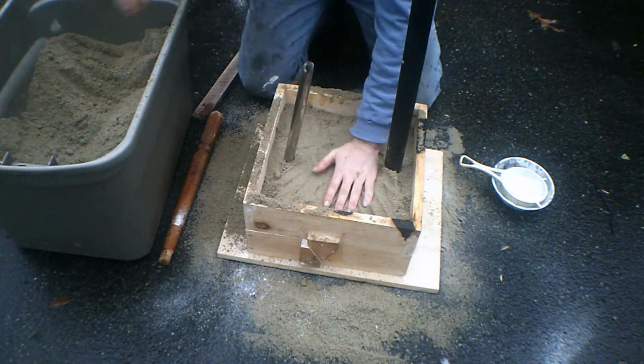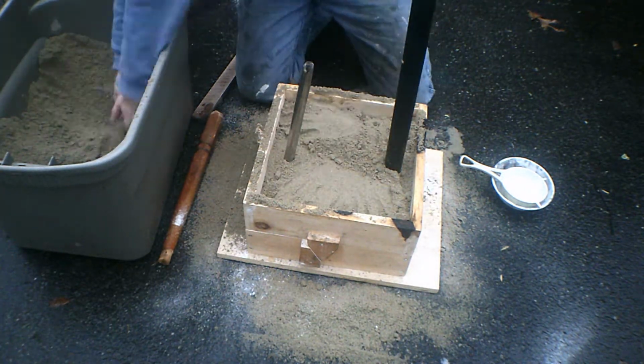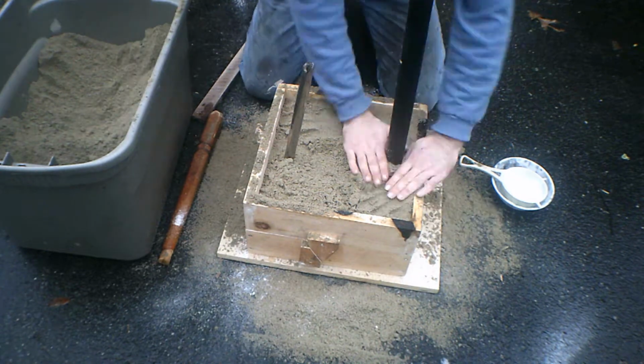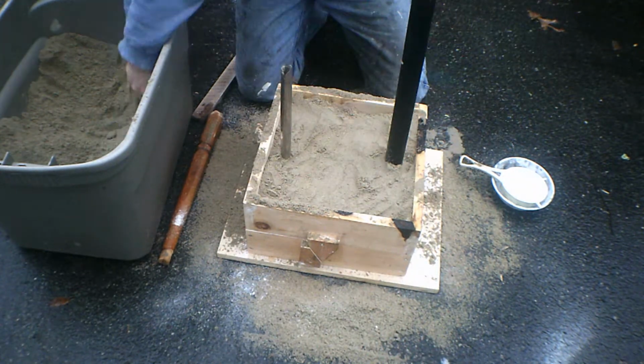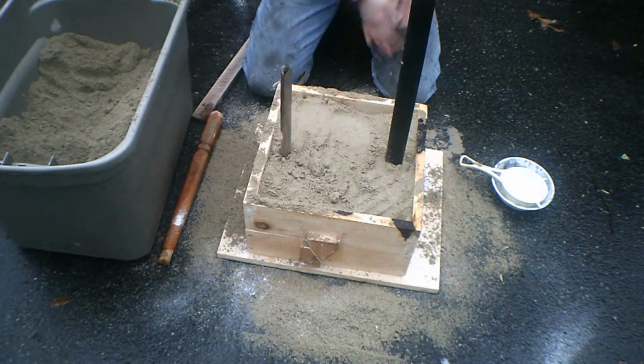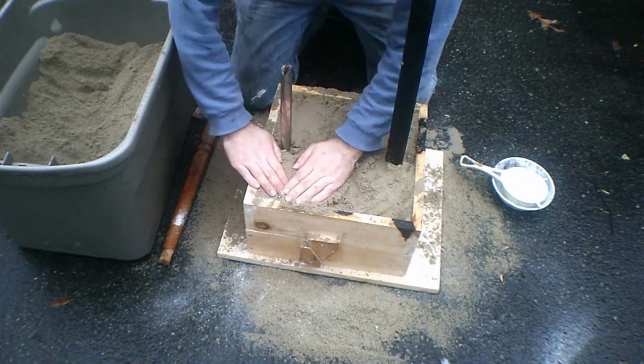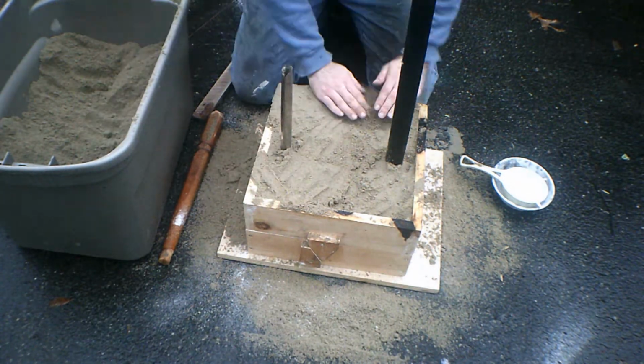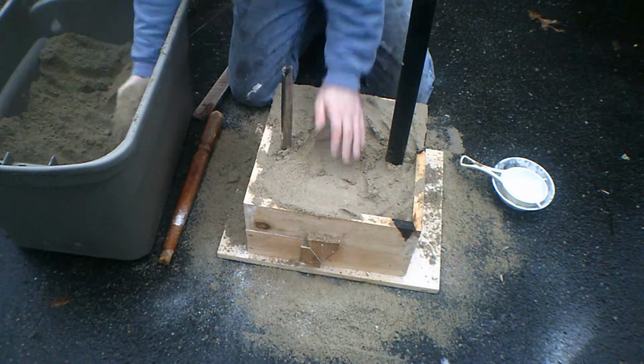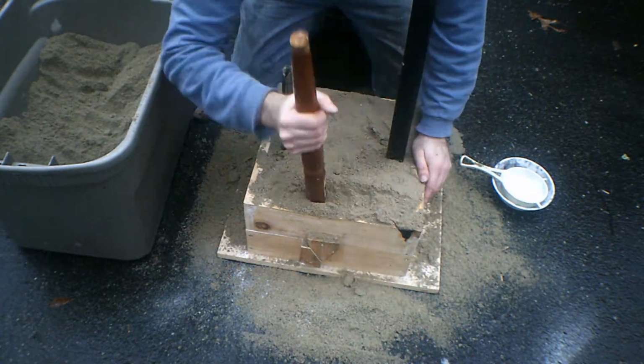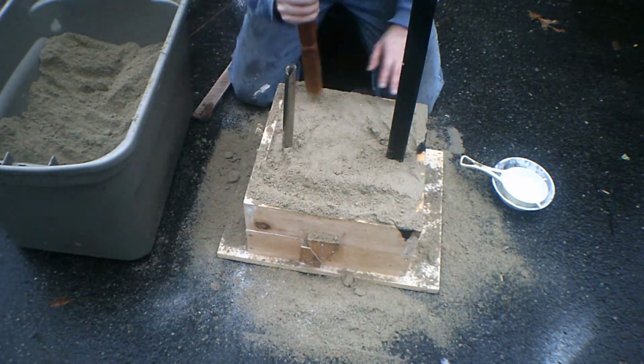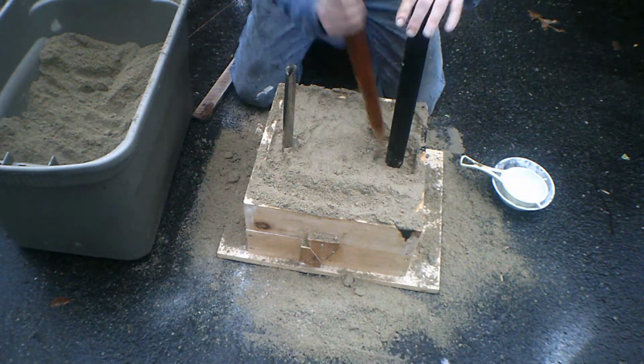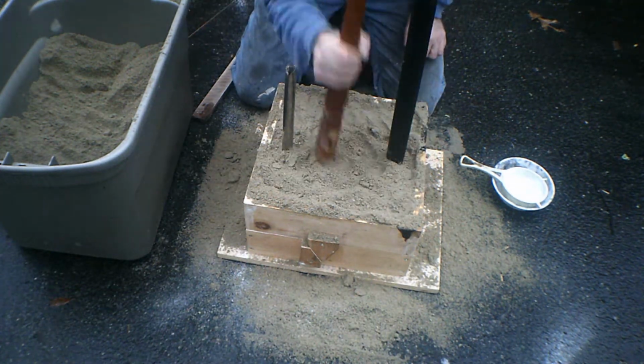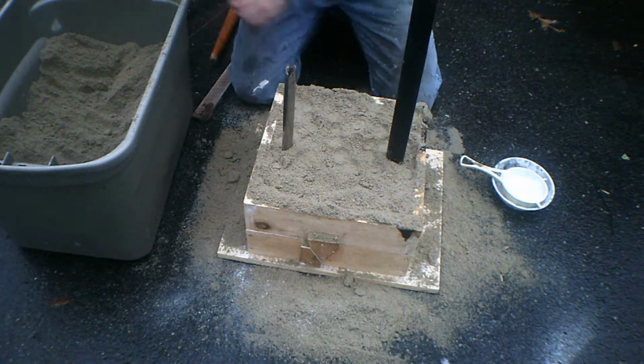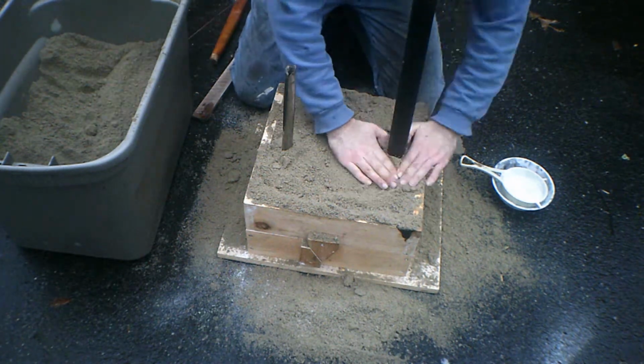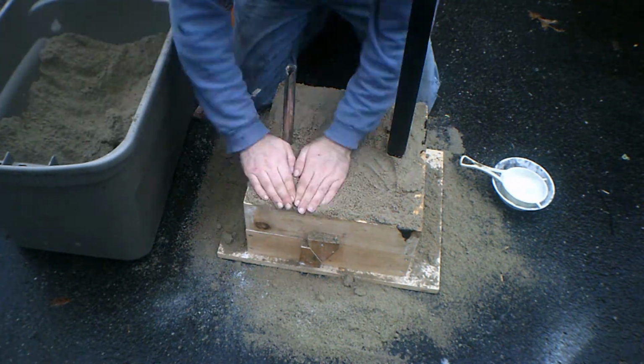Again, ideally I would have riddled that sand, meaning broken it up through a screen, but once more, by hand is good enough for my application. And then I just pack it around the two pipes that I'm using to mold the sprue and the riser. Again, ramming up, I'm flipping the ramming tool over to get in really close around those two pipes, and then ramming continuously around everywhere else.